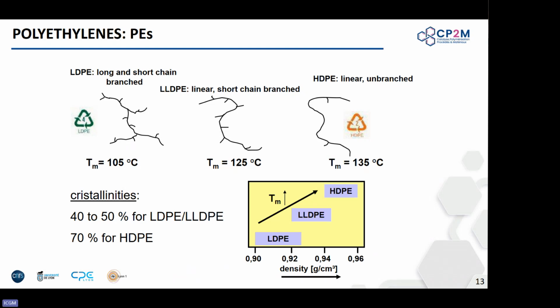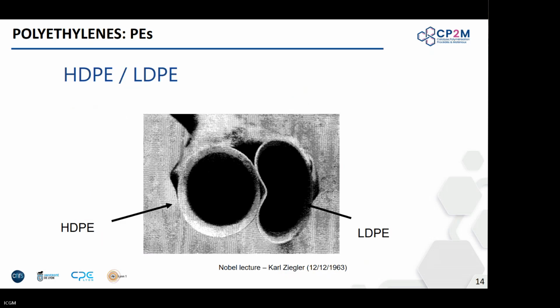Here there are more C4 branches, but here you can have C4. You can also have C6 branches if you copolymerize with octene, for instance. And HDPE, mostly linear, and a melting temperature, okay, it can be slightly upwards of 135. You can reach 136, 137. It depends. Crystallinity, these are just rough ideas that you can bear in mind: 40 to 50% for an LLDPE, for instance, slightly lower for an LDPE, and 70% for an HDPE. And the density, of course, rises when you increase the crystallinity.